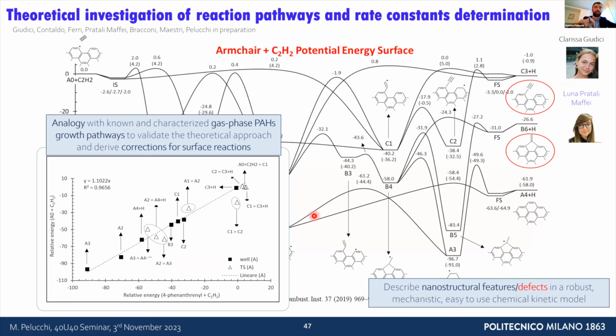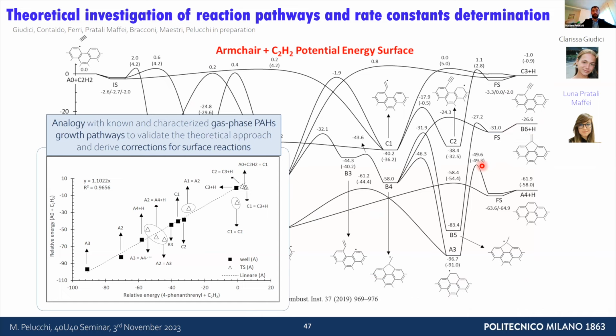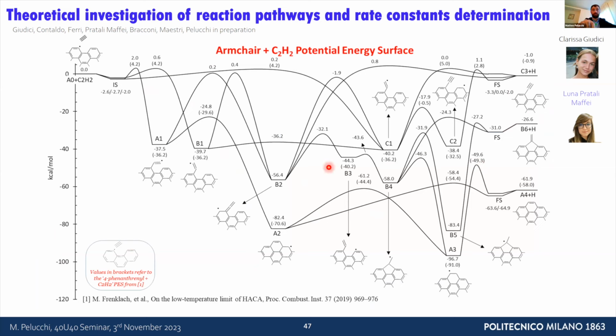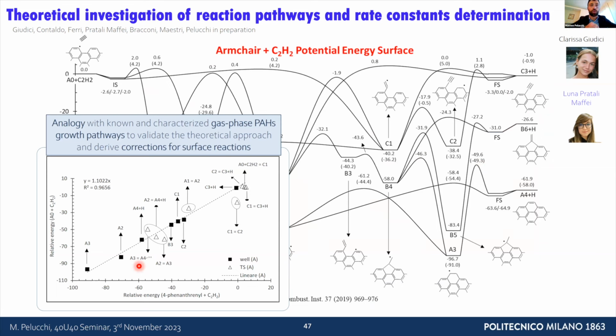The aim of exploring this potential energy surface is, one, to define rate constants for the heterogeneous gas-solid reactions using climbing image nudged elastic band, but also to find shortcut ways to determine those rate constants. So if I know the gas phase analogy—this example refers to work from Michael Frenklach and co-workers on the 4-phenanthrenyl plus acetylene potential energy surface—we can draw some sort of Bell-Evans-Polanyi plot. Then, if we know the barrier in a gas phase reaction for which we can adopt a very accurate method, we can transfer it to the equivalent gas-solid reaction by applying a correction to the energy barrier and to the entropy factors.